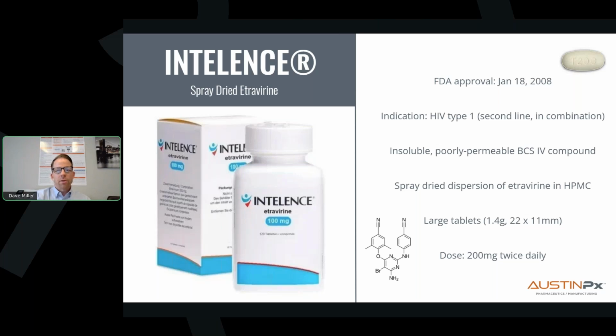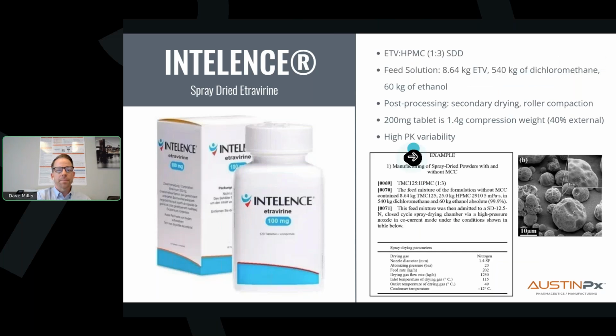Because of that relatively low loading and the need for external excipients in the tableting phase of the SDD product, each of the 200 milligram tablets weighs about 1.4 grams compression weight, and the dimensions are 22 by 11 millimeters. So it's a very large tablet at the higher dose. Patients have to take 400 milligrams a day, so they take these 200 milligram pills twice daily, which is not the most convenient therapy. Beyond this, the product also shows relatively high pharmacokinetic variability. So ultimately, the product and the process work, but it's definitely not elegant, and these large tablets are not patient-centric.